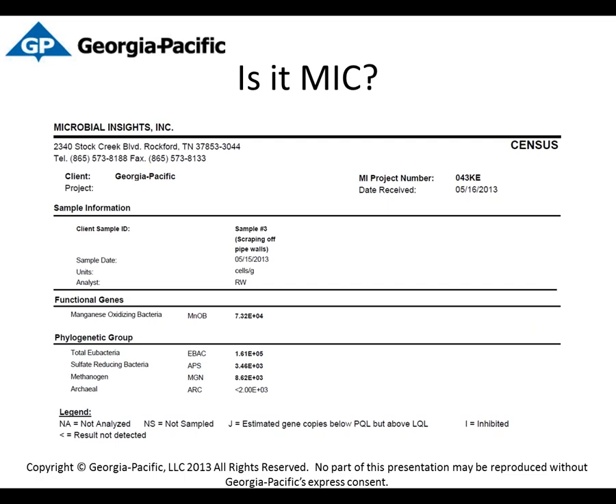And with the sulfate-reducing bacteria, it's a common misconception that if you start doing any research on MIC or hear anybody in industry talk about MIC, everyone immediately jumps to SRB or SOB, sulfate-reducing bacteria or sulfur-oxidizing bacteria. Everybody immediately jumps to those two and says those are the ones, because they can, through their environment, create H2S and sulfuric acid. So everybody thinks, well, that's the most corrosive. If you don't see either one of those two species or that group of bacteria, you don't actually have MIC and you're not getting corrosion. Well, we found that to be completely false.